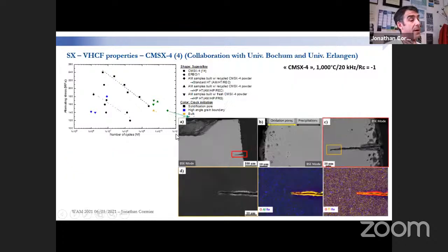And all the other specimens failed from the surface through an oxidation process. So that's the longest ever test we did, which lasted more than 500 hours. When we are able to get rid of pores, then we have crack initiation from the surface controlled by oxidation. So it means that in those conditions at high temperature, probably we have no fatigue limit. If we decreased the alternating stress, we would have a progressive decrease of the applied stress.